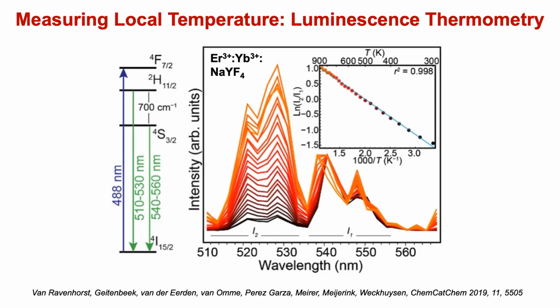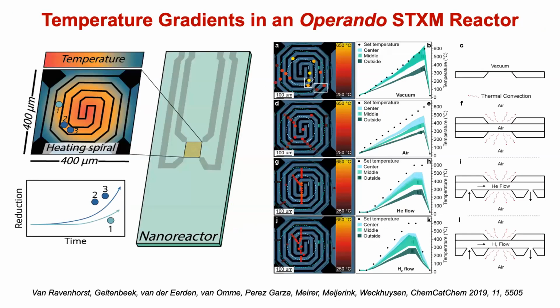So what we did is we sprinkled these crystals into this cell, and now you can analyze 1, 2, 3. Here you see more of these particles, which we have defined. In the middle, you see particles A to J in different colors, and you have 3 zones: zone 1, zone 2, zone 3. 1 in the middle, 2 a little bit further, 3 in the surroundings. You can already anticipate what I'm going to tell you.